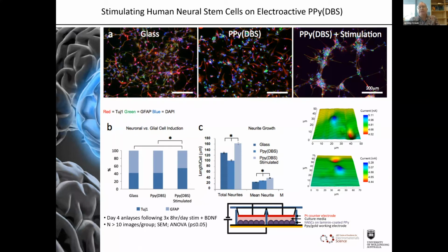Now, importantly, cell clusters showed a similar spatial distribution to regions of higher conductivity on the polymer film surface, which suggested the level of conductivity and therefore stimulation influences cell adhesion and/or galvanotaxis. While for now we can only surmise, our findings are consistent with using modulation of conductivity and electroactivity of polypyrrole or other conductive polymer-based substrates used to grow and stimulate cells to regulate the maturation and organisation of neural networks in vitro and in vivo.